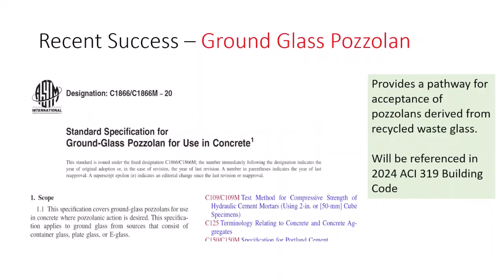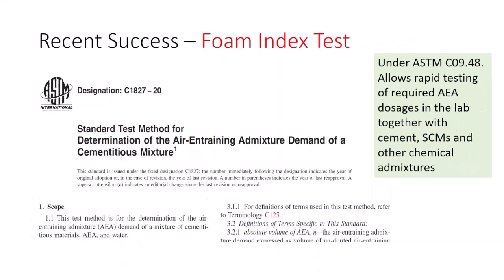And we have a standard for it, which we're hoping to incorporate in a performance spec for SCMs. We got the ground glass pozzolan standard in 2020, which allows municipal waste glass recycling operations to process and grind the glass and make it into a pozzolan. There's about, I think, 3 or 4 plants in the U.S. operating now, but the total capacity is still under 1 million tons, so it's not a huge quantity. And there are some issues with using it in terms of its high alkali content, in terms of ASR issues.